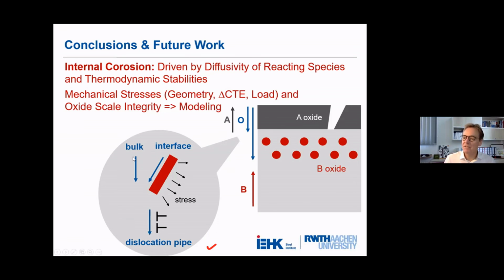If you have a closer look, then we also have intrinsic effects. So diffusion can be enhanced by diffusion along the interfaces. The diffusion can be driven by the occurrence of mechanical stresses due to the higher volume of the internal precipitates, which causes an increase in the dislocation density, and then an increase in dislocation pipe diffusion. That is what we are right now trying to implement in our numerical approaches, which gives us a bit more freedom than, for instance, the analytical model of internal oxidation as suggested by Carl Wagner in the late 50s.